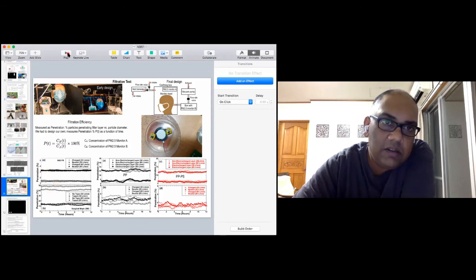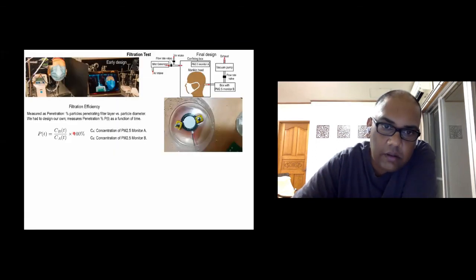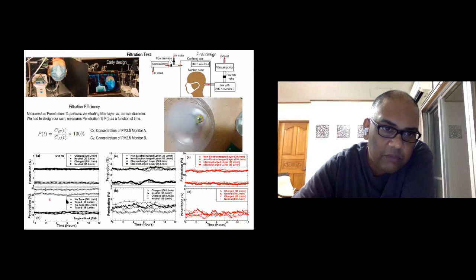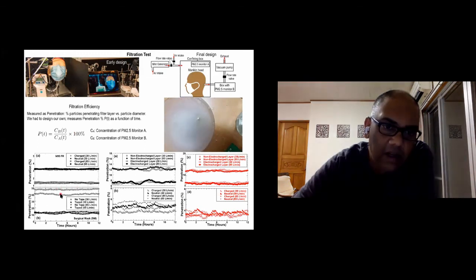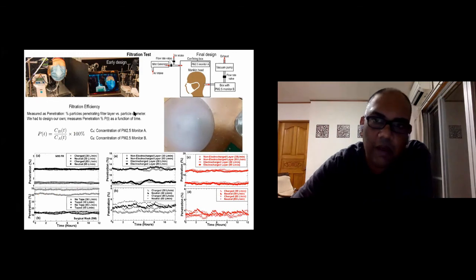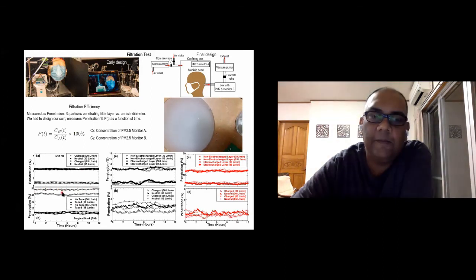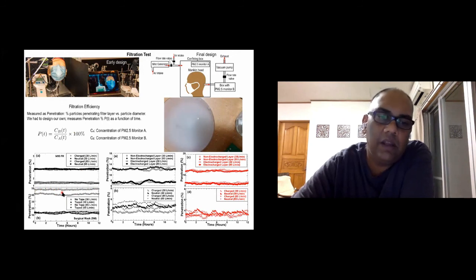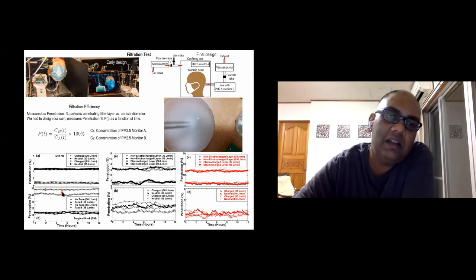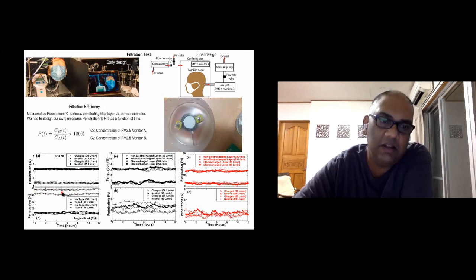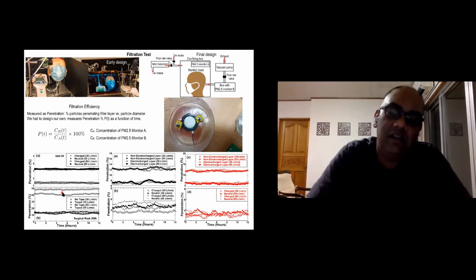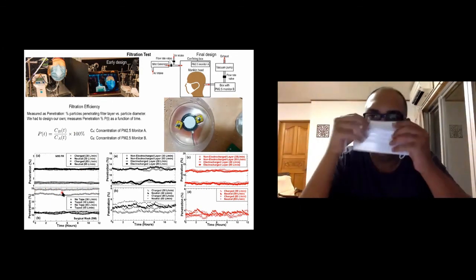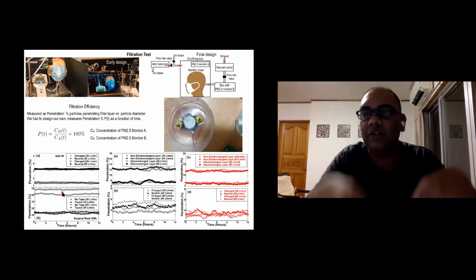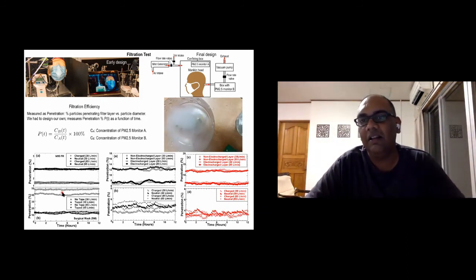So you see the bottom left plot. This was for a surgical mask, and if I just put the mask on the mannequin head without taping it, roughly 50% of the particles are able to pass through. So they don't do so well. And this study was showing that cloth masks were also behaving similarly. The take-home point is that it has nothing to do with the quality of the mask, but the gaps in between. Because you don't have a tight facial fit, the penetration increases.